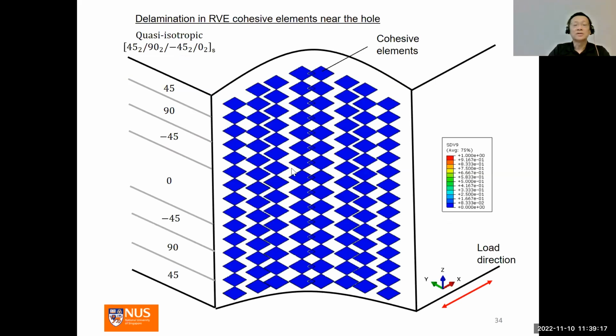The animation has stopped working, but anyway, the animation is supposed to show the cohesive elements with colors here, indicating that possible delamination has occurred in some of the interfaces. The picture here actually shows only the cohesive elements of the RVEs. The blocks of plies are not shown here.